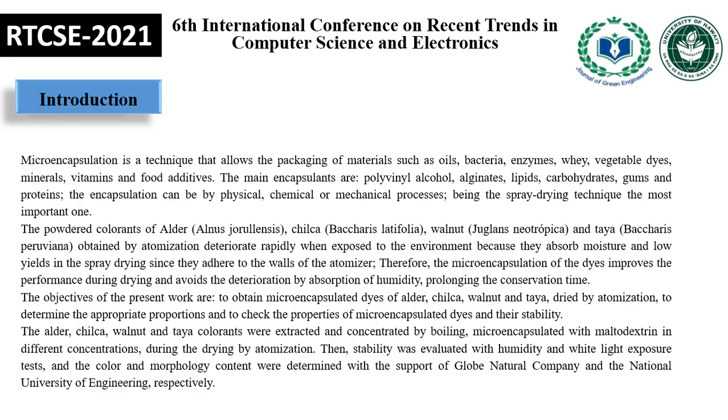The alder, chilca, walnut, and taya colorants were extracted and concentrated by boiling, and microencapsulated with maltodextrin at different concentrations during the drying by atomization. Then, stability was evaluated with humidity and white light exposure tests, and the color and morphology were determined with the support of Globe Natural Company and the National University of Engineering respectively.